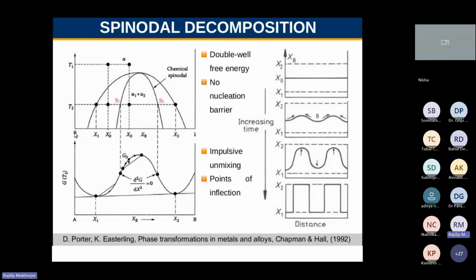Like if you take a composition, the left side is an A-rich phase and the right side is a B-rich phase, right? These are two defined chemical elements. But if you mix them together, say at a composition of X0, these are basically mole fractions, that's why it is written 1, right? If you go to a temperature T1, you will get a phase which is alpha. But if you go to temperature T2, spinodal decomposition will take place, and this alpha will decompose into alpha 1 plus alpha 2. So if you take this X0 composition at temperature T1, then quench it to temperature T2 and hold the alloy at this temperature, it will decompose into alpha 1 plus alpha 2, like the previous figure you have seen, where it decomposes into orange and purple phases, right?